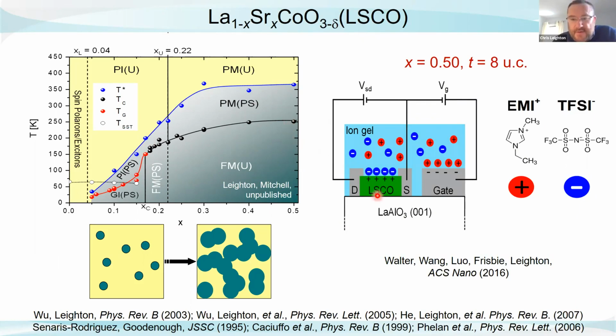We're going to make thin films that are deposited on a lanthanum aluminate substrate. They're going to be exactly 8 unit cells thick. 1 unit cell less than that, we start to get dead layer problems, so we can't maintain ferromagnetism so easily. And then I really want to emphasize, we have a side gate. That means that we have put the gate millimeters, in some cases centimeters away from the channel. That dramatically slows down the operation of the device by many orders of magnitude.